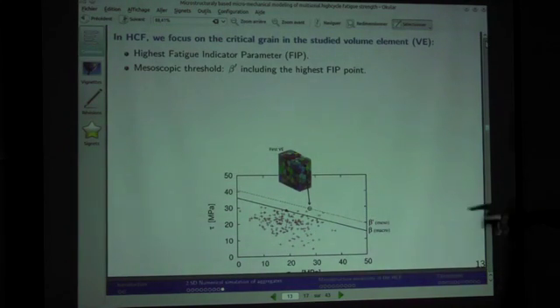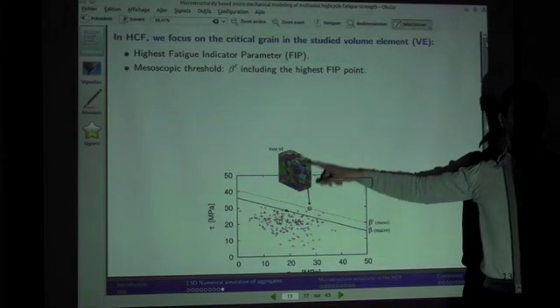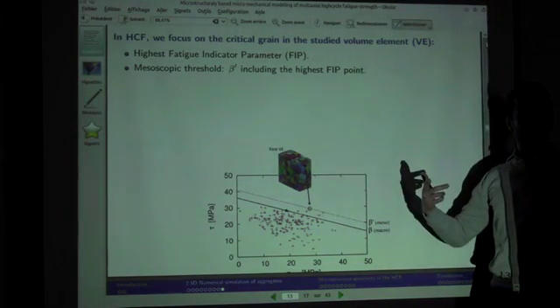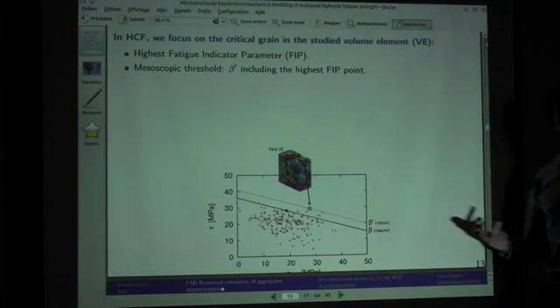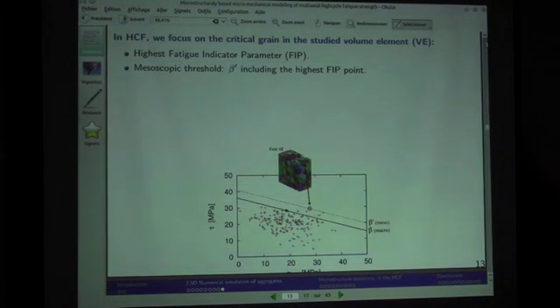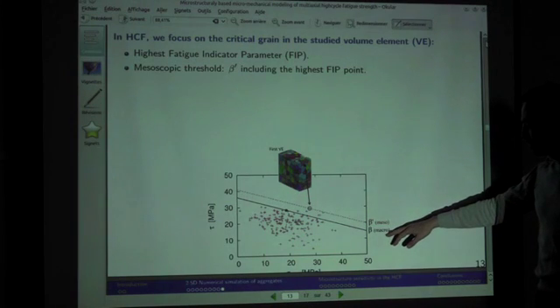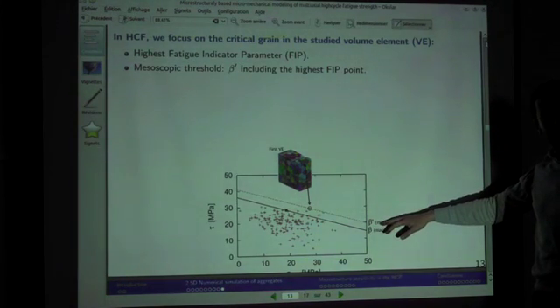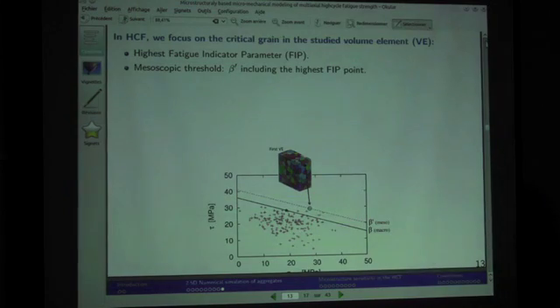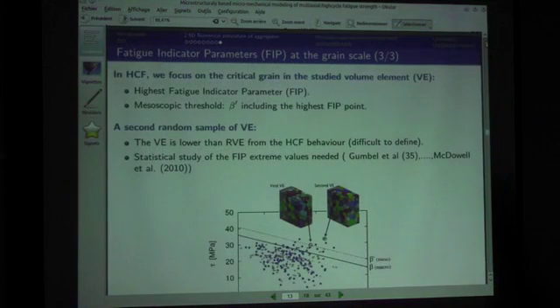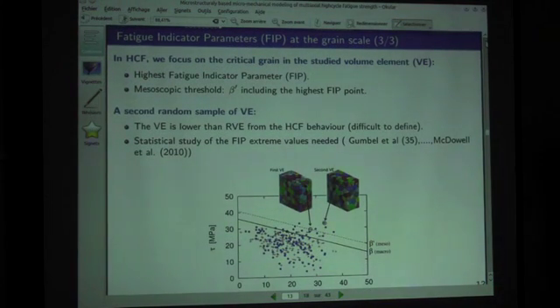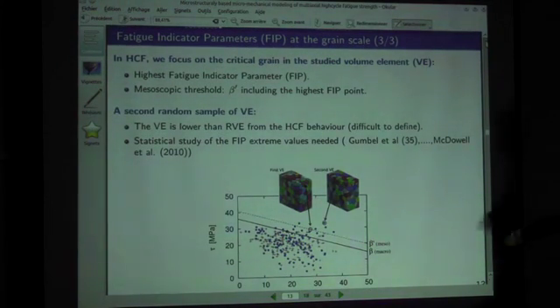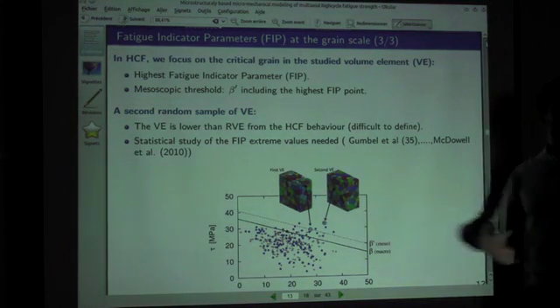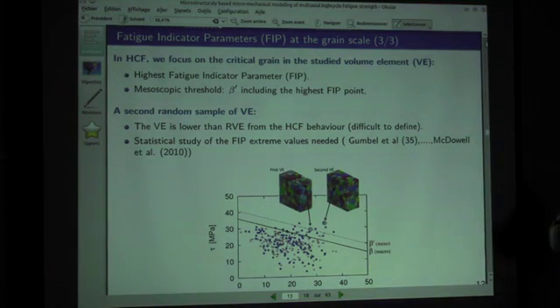And this new threshold will be going through the point that is the most heavily loaded in the aggregate according to one fatigue criterion. So we say, okay, we are not going to use this macro threshold anymore, we're going to use this meso threshold, which is more related to the microstructure. The problem if you do this is that if you compute another aggregate, you will have another maximum here. Well, this is a problem because you are not statistically representative using only one aggregate.